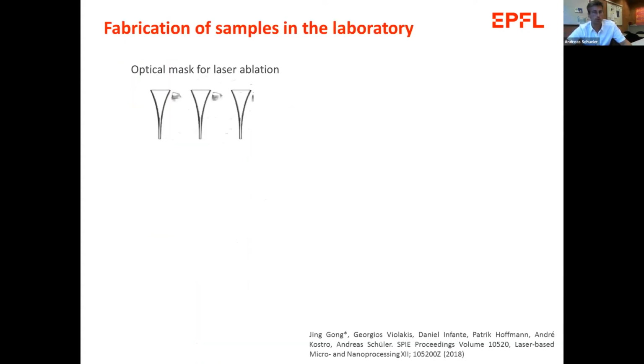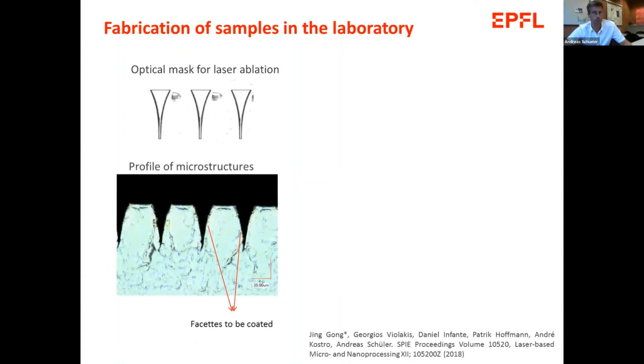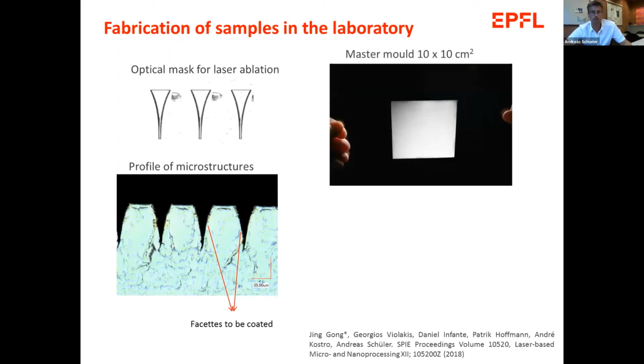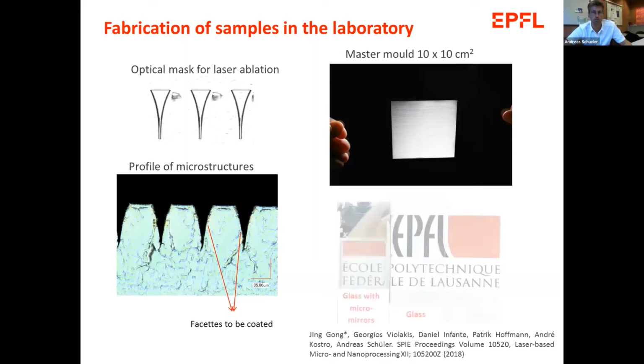So we start with origination, we make a mask for laser ablation, we do the laser ablation in collaboration with EMPA and TUN. And then we obtain this master mold, we will replicate it, and here is a snapshot of the master mold. So we took a polycarbonate sheet and we did this structuring by laser ablation. And already the master mold shows this property of light redirection, which is shown here in the image.